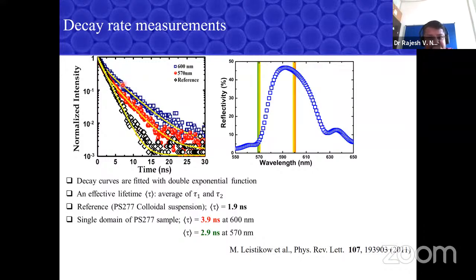If you measure from the stop gap region, at 600 nanometers, the blue symbols here, and fit with the double exponential, the lifetime is around 3.9 nanoseconds. So the lifetime is reduced. That means the decay rate is slowed down. Sorry, the lifetime is increased. That means the decay rate is reduced. That's why the decay becomes slower when you measure at the band gap.